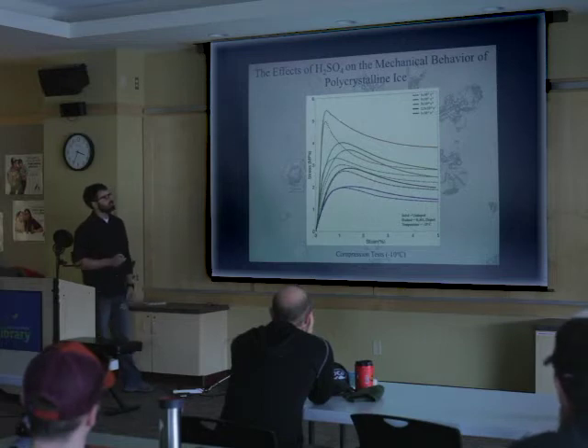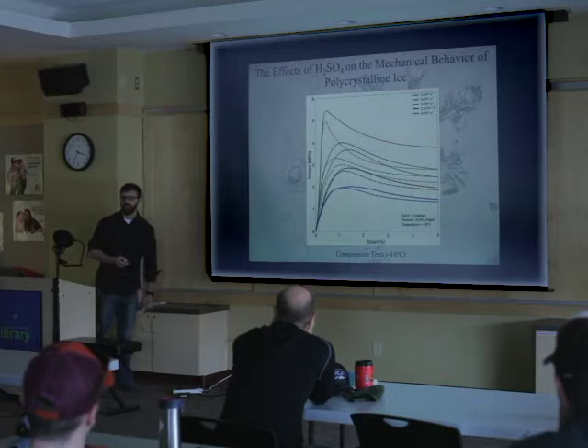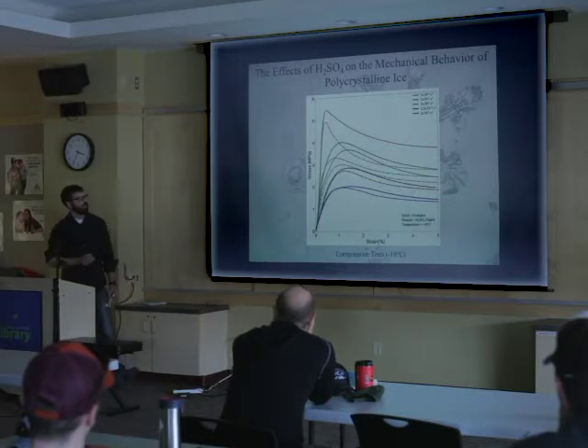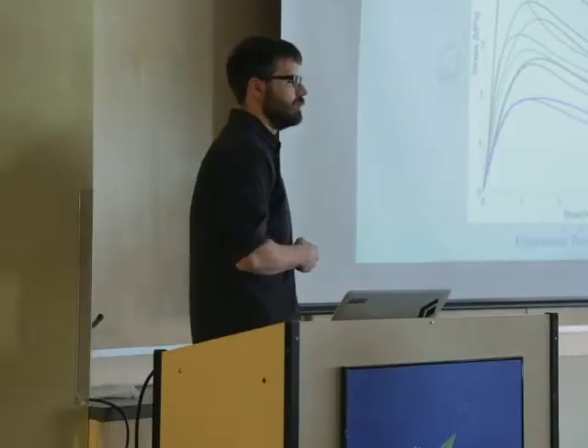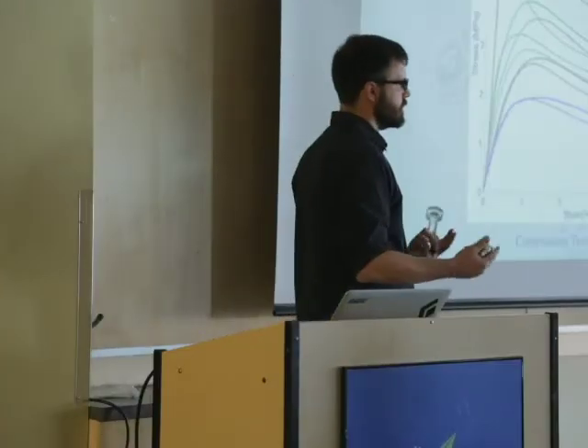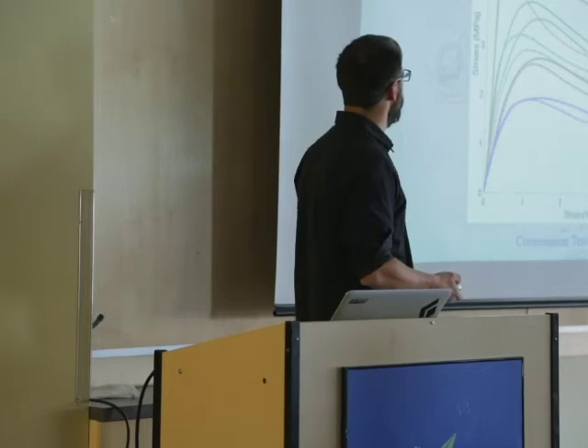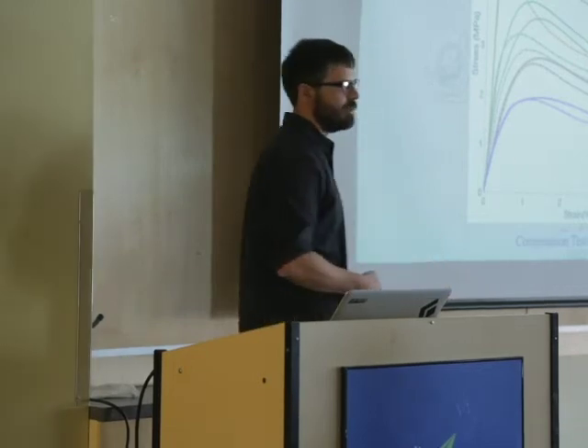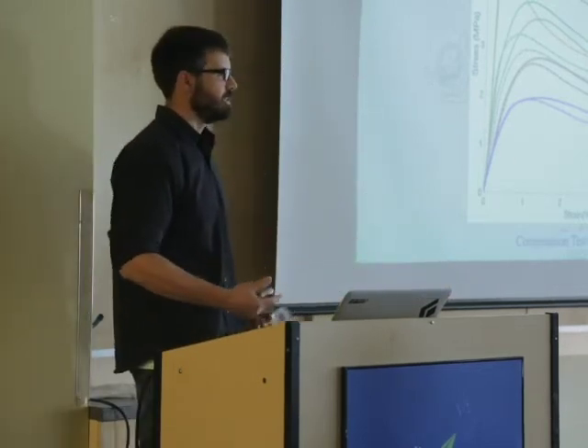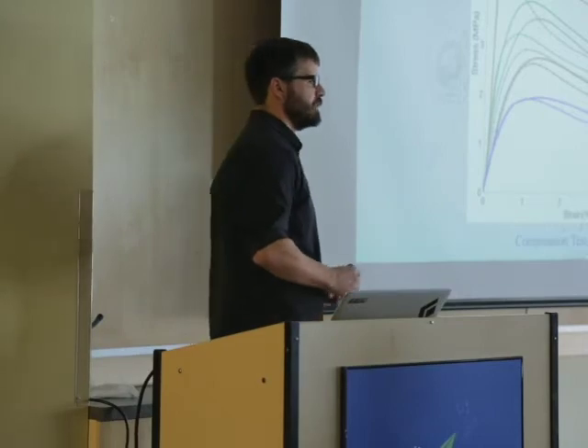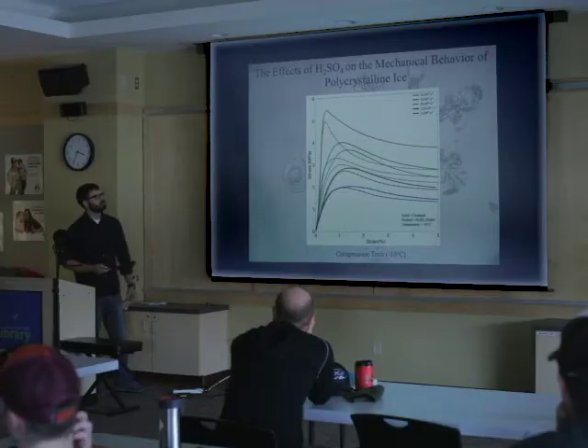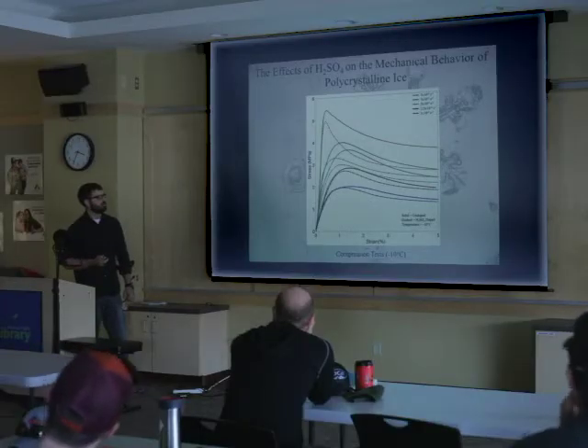You always see a decrease in the strength of the ice whenever it has this little bit of sulfuric acid in there. It's pretty obvious at all strain rates until you start getting down to the really low strain rates, where there's a shift in the mechanism. I don't want to get too much into that, but looking at this plot, bottom line, sulfuric acid, even in these trace amounts, has an effect on the mechanical properties and the strength of the ice, which I thought was really pretty interesting and pretty cool.